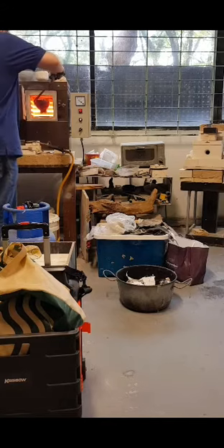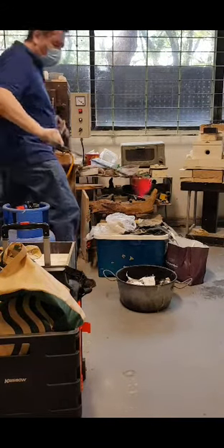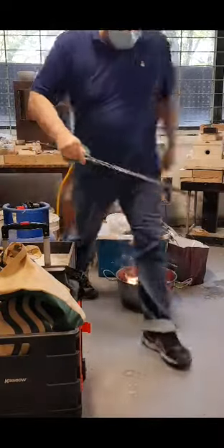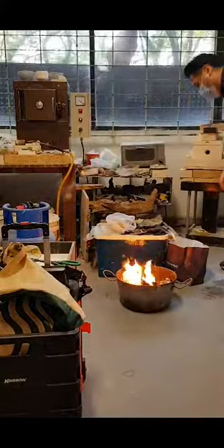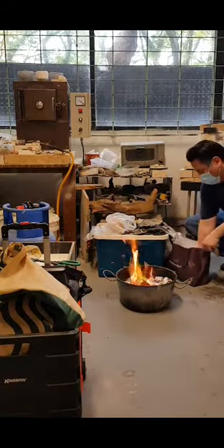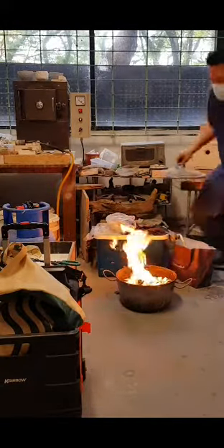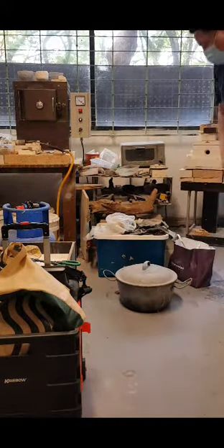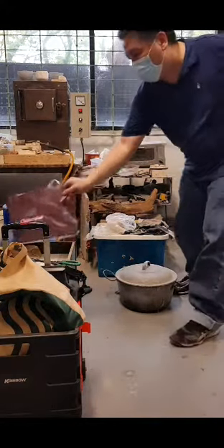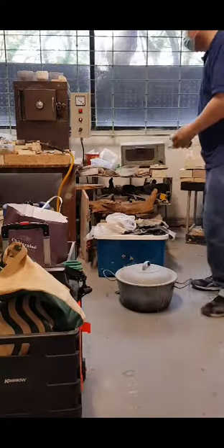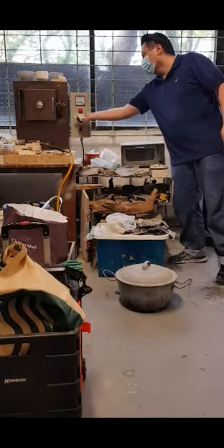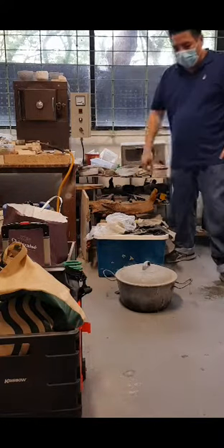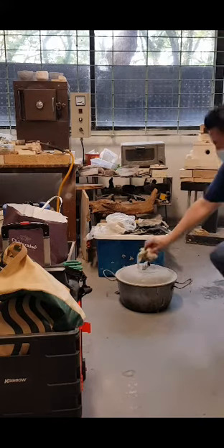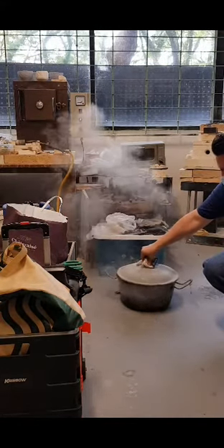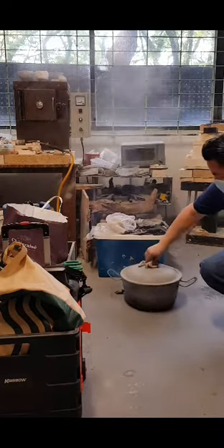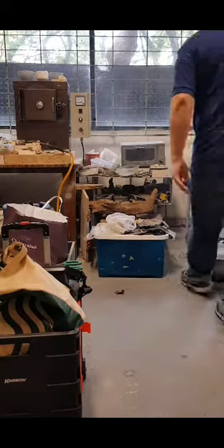The pot is very hot, so I'm taking it with tongs and carefully putting it in there. The paper is going to start burning, and I'm going to put a little more scrap paper on top of it, just to make sure everything is covered up, the whole smoke is covering it up. Then I'll close it up. The fire will still be burning, but because it's lacking oxygen, it will start creating smoke, so you can start seeing a lot of smoke coming up from the side of the can. And that's what you want. You want a lot of smoke to get the post-reduction happening. That post-reduction is the one that will react with the glaze that has a lot of copper oxide in it to make the results more lustrous, more metallic looking.